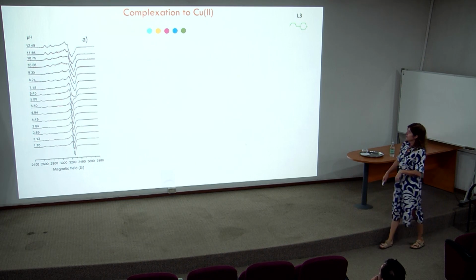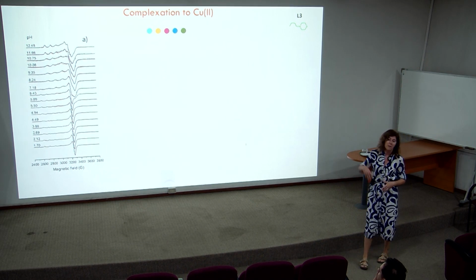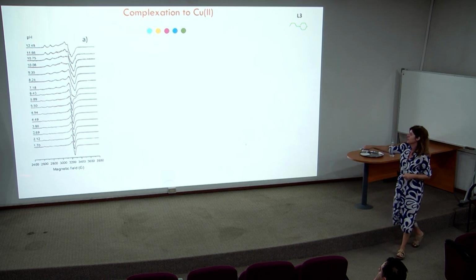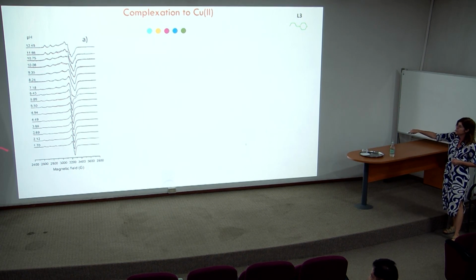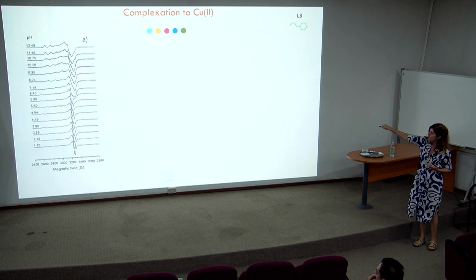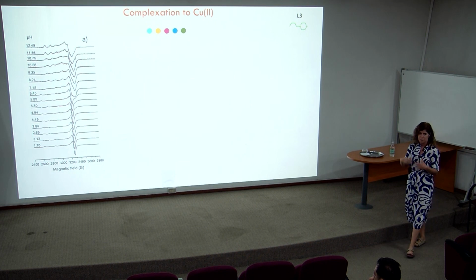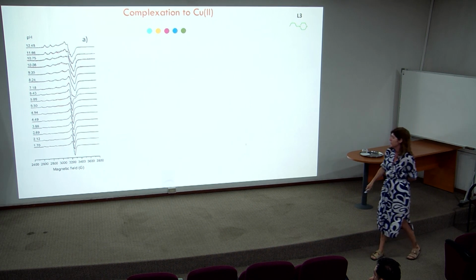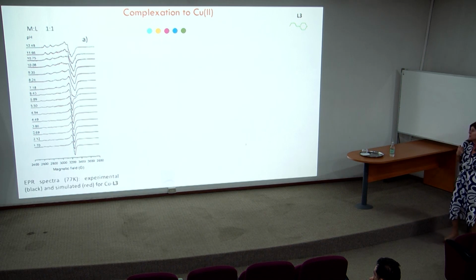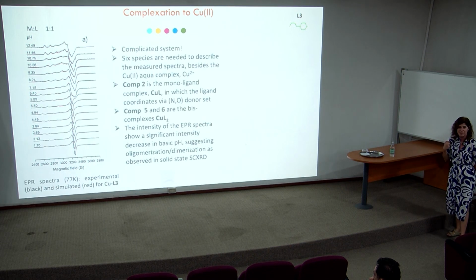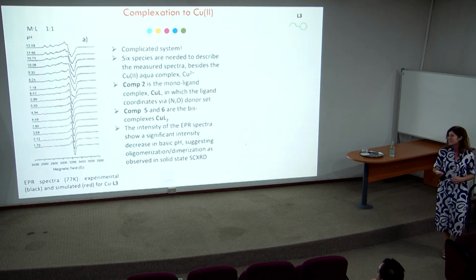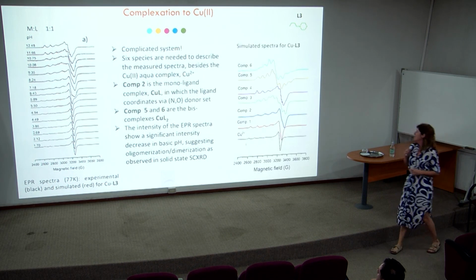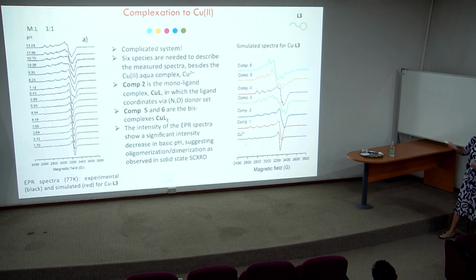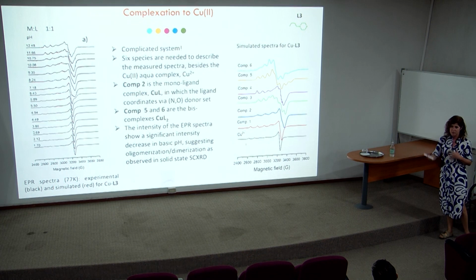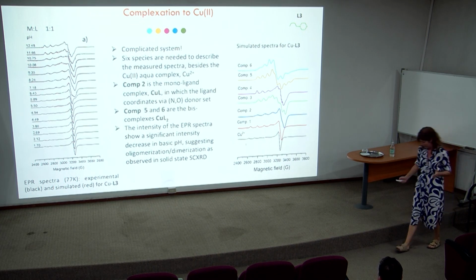Of course, we studied the complexation. We corroborated it by EPR studies. You have here the EPR measured at different pH values. The figures that I showed you before were focusing only on this region, which is the region which is informative and gives you information on the binding of the compounds to the metal ion. I'm not going to go into any details. This was a very complicated system. So we were not expecting such a complicated system. But we could simulate the spectra corresponding to all the components that were found in solution in the different pH range.